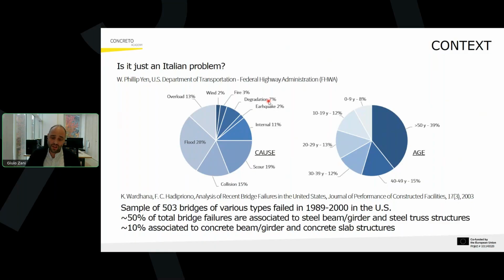According to another study, again from the United States, in which the researchers studied samples of 500 bridges of various types that failed in 1989-2000, so a little more than 10 years, they observed that about 50% of total bridge failures were associated with structures made of steel and not of concrete, as we observed for the Italian case. In this particular sample of bridges, only 10% of failures were associated with concrete-based structures.